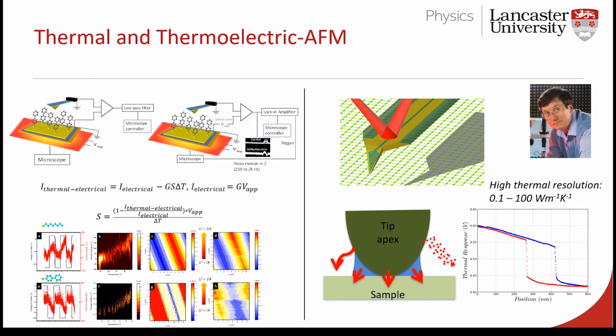So this is, again, using our non-destructive characterization capabilities. And now we're taking our material of interest and we're applying a temperature gradient to it. So we're warming up one side. So one side is hotter than the other. We then land our scanning probe on the surface. And if you've chosen your material correctly, most semiconductors, most organic materials will exhibit something called the Seebeck effect. And this is the generation of an electric voltage, thermoelectric voltage from that temperature gradient. There's a huge push around the world at the moment for thermoelectric materials. It's seen as being one of the potential answers to the carbon crisis we have at the moment, and a key aspect of this aim to be carbon neutral by 2050.